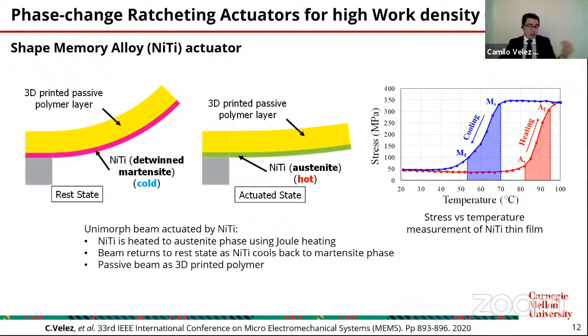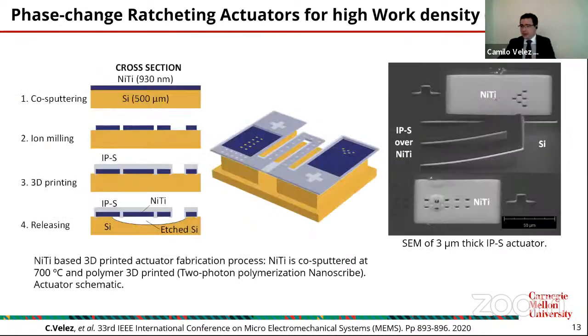So guess what? The passive layer that we are going to use is a 3D printed material. For this experiment, we use common microfabrication. We have a silicon layer, and we co-sputter nickel titanium at a more or less 50-50 ratio.